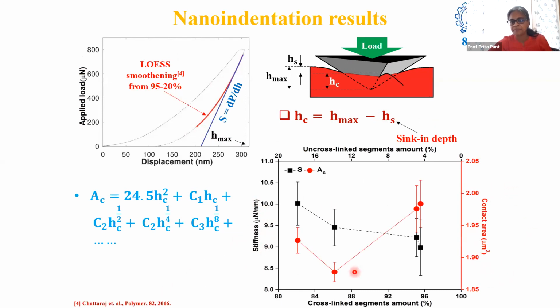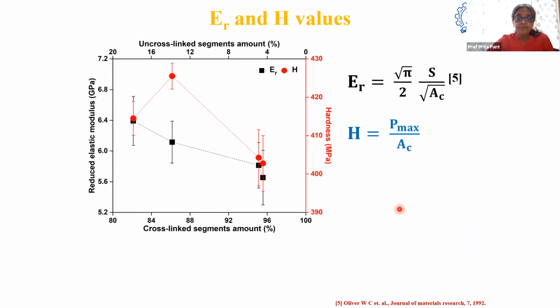And this is the point at which we started to get a little concerned. So here is the stiffness, the slope of the unloading curve, and this is counterintuitive. We had expected that the higher the level of cross-linking, the stiffer the sample would be. But that's not what we are finding. Okay, we are finding that the more cross-linked samples have a higher contact area. We are calculating a higher contact area, and we are measuring lower stiffnesses for them. Now, this combination of a lower stiffness and a higher contact area, of course, gives us a lower modulus for the more cross-linked sample.